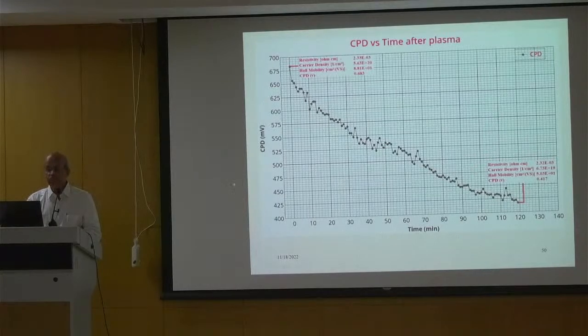The moment we took the sample out of the plasma chamber and put it into the Kelvin machine, it started showing 678, 680 millivolts as contact potential difference. Over a time t, meaning I just took it from the plasma chamber, kept it in the open along with the Kelvin machine, and started measuring the CPD. You see that CPD falls down as a function of time. We measured up to 120 minutes. The Kelvin machine, we made it automated, so it started recording it.